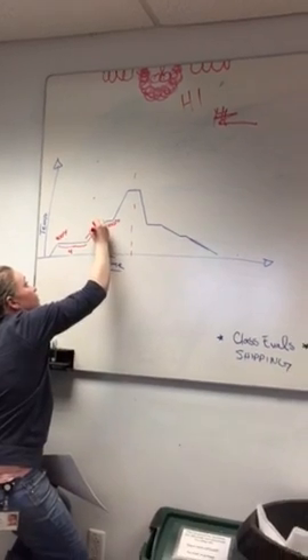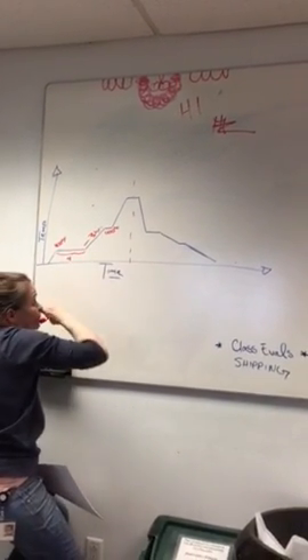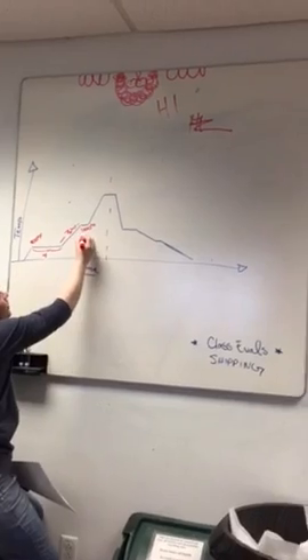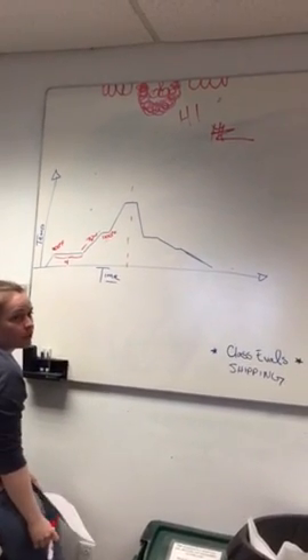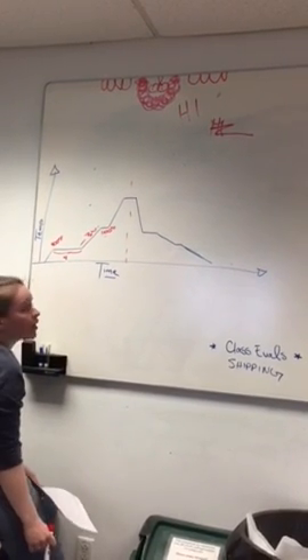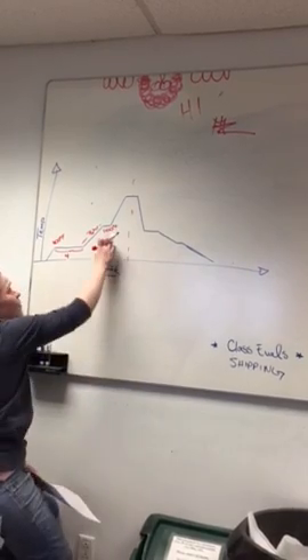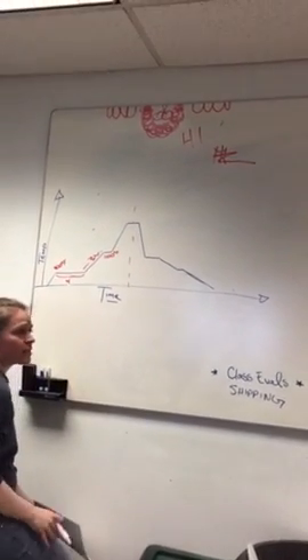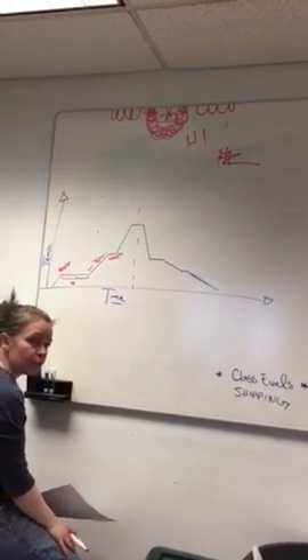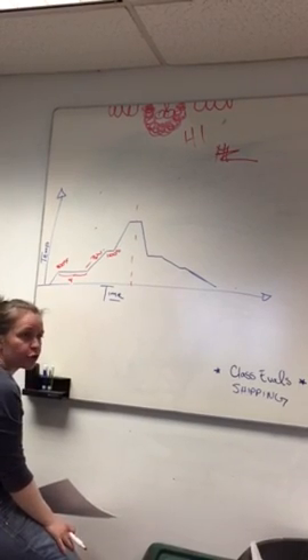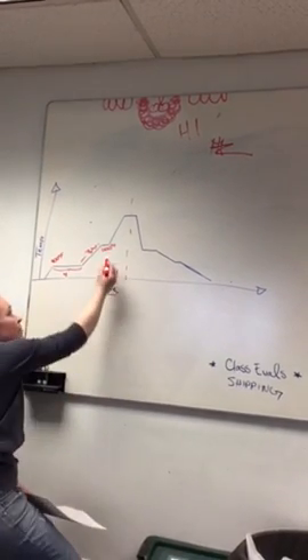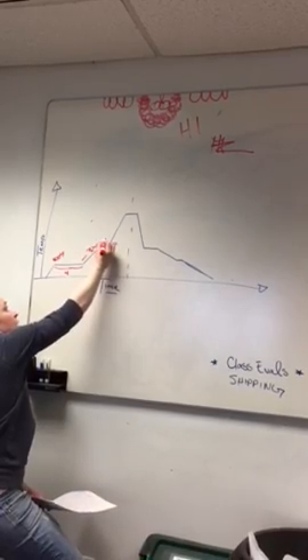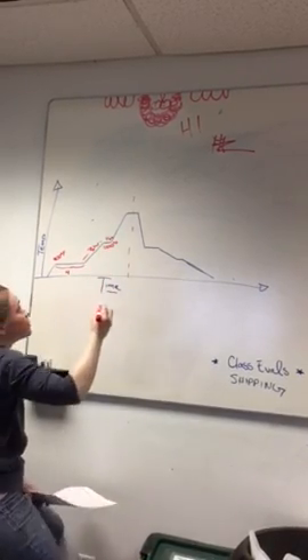over 3 hours for this mold. At 1100 degrees is going to burn out your chemical water. It's going to kind of cure your mold, make it a little stronger. It's also the temperature at which Bullseye starts to sag and slump a little. So it also can work as a bubble soak if you're fusing larger sheets of glass together. So it's a nice temperature for both of those reasons. And we're going to hold there for a half an hour.